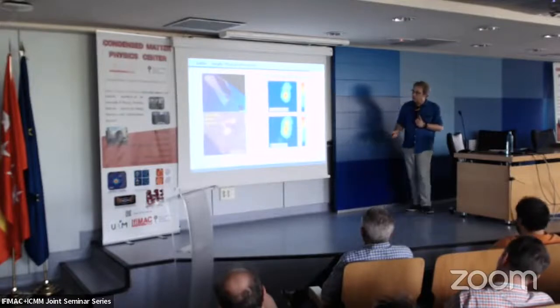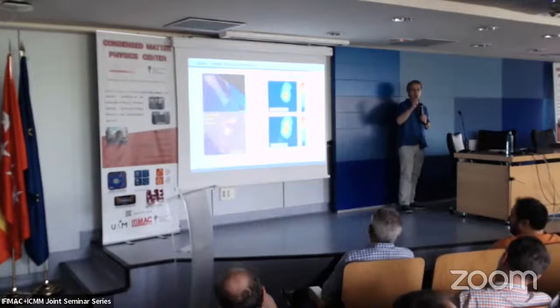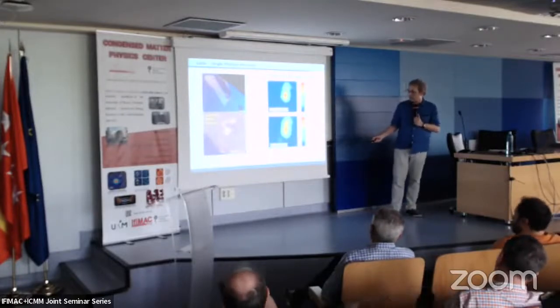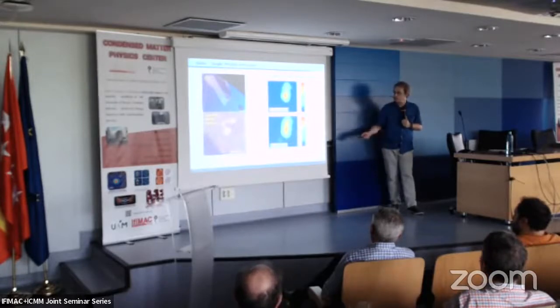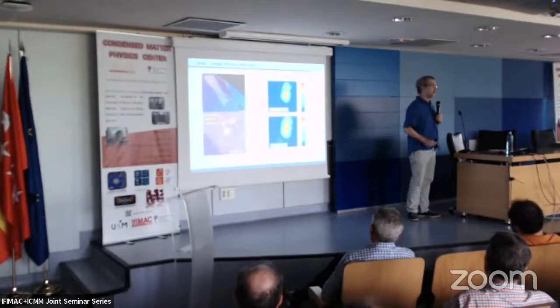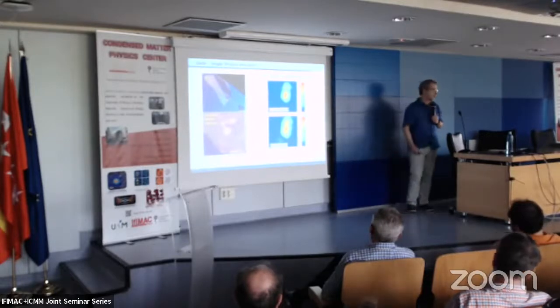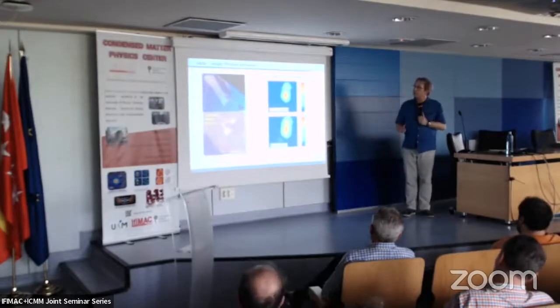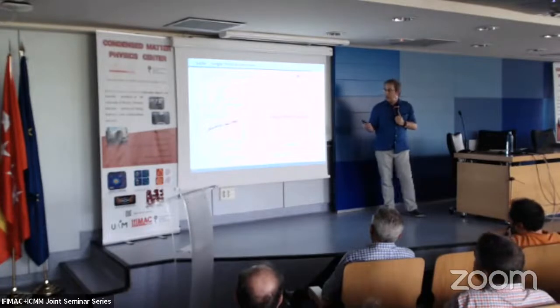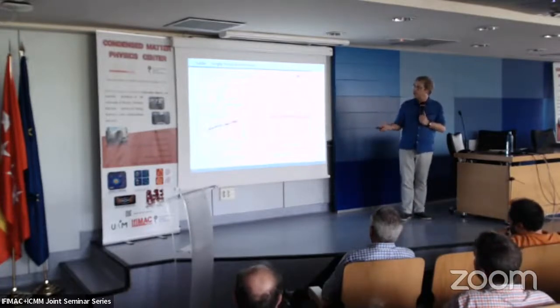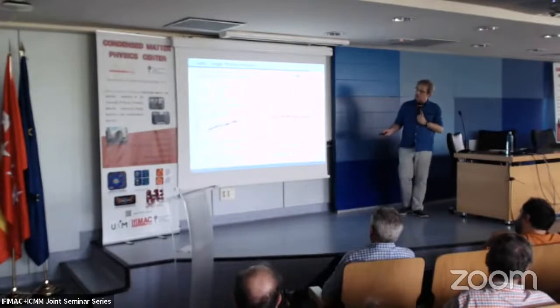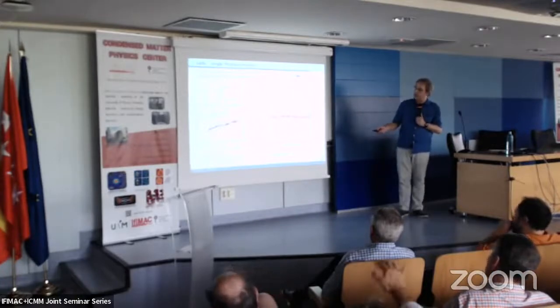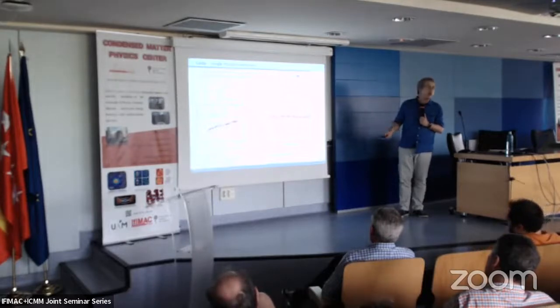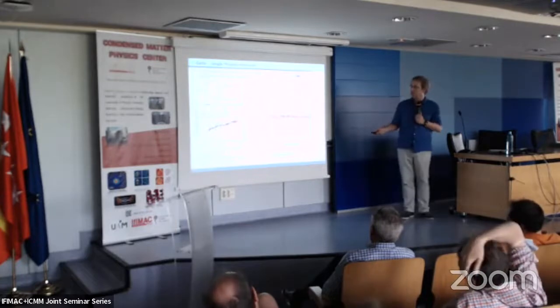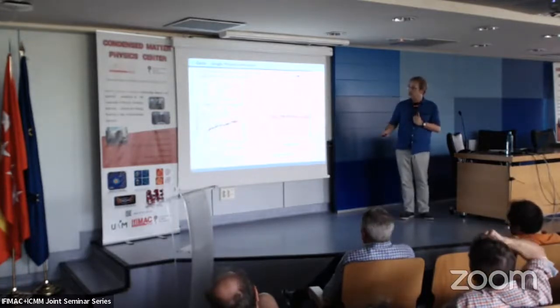The single photon emission originated from this point. And here are intensities which are really localized on this one. As you see, what's here is a micrometer scale. The spatial resolution is determined by the laser spot of 1.5 micron on the sample. So this is where we could find single photon emission, and we found the emission of both an exciton and a bi-exciton, which is depicted here in the scale, the power dependence of the emission. So we can see that this is a little bit sublinear, and this is the double slope of the exciton. So that is really illustrating that this is a bi-exciton and this is exciton.